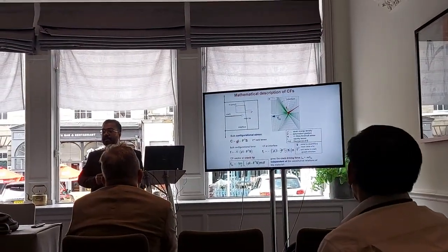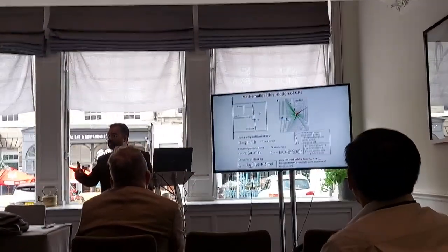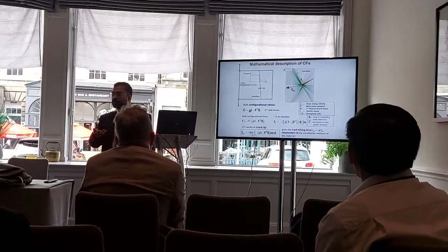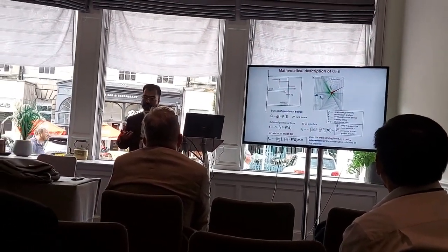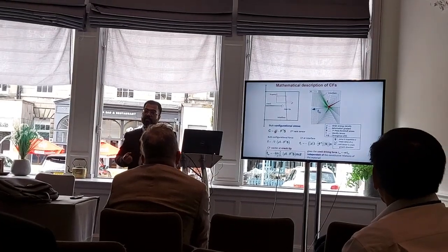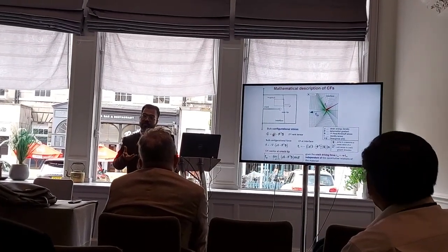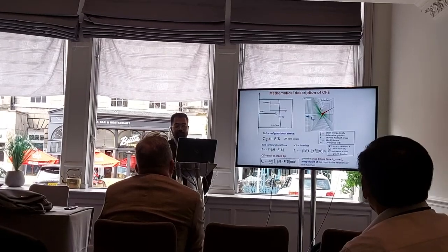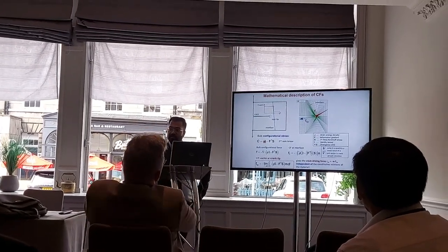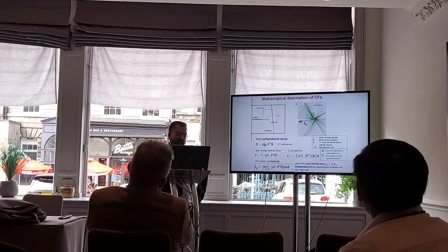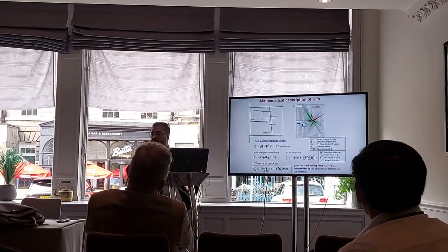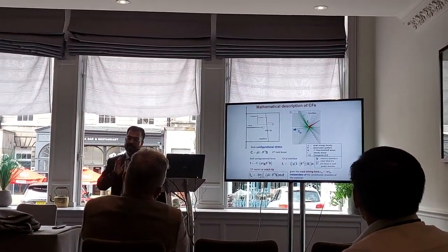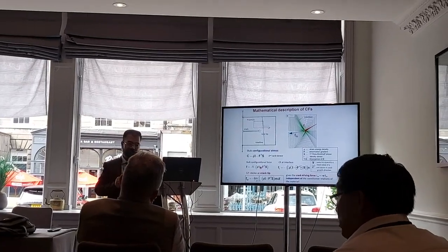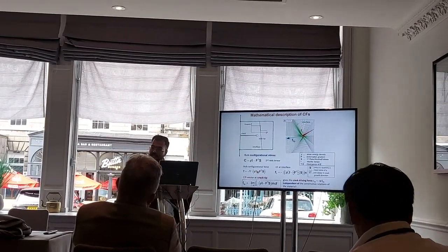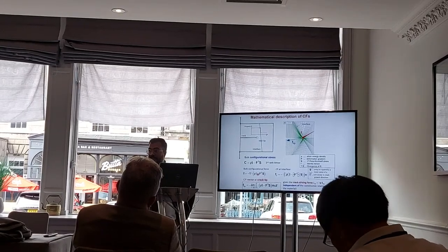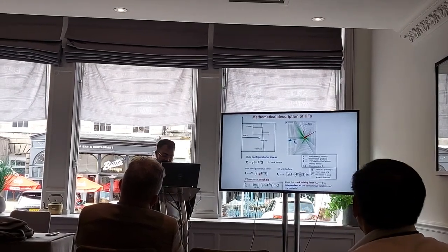The truth is that plastic energy, whether it is time dependent or independent, cannot be used for crack growth. So that cannot be a crack driving force. Only elastic energy can provide the driving force for the crack to grow. So in order to do that, we include only the elastic strain energy density in phi, and we calculate F, and we sum them up, and then we project it towards the x1 direction, if that is the expected crack growth direction, so you get a scalar value of J. Otherwise, it's a vector, so you will have two components.